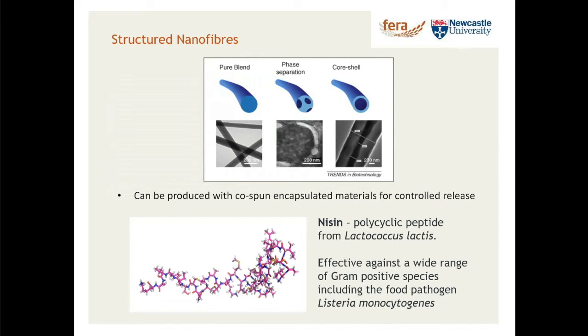So other things we can do with this process, we can spin fibers, but we can also start to spin fibers which contain various other materials as well, and these can be randomly distributed or in a more controlled fashion. And that's kind of interesting because then we now enter into the realms of creating materials which are perhaps biopolymer based, which contain other materials which could also be biological and also released from the fibers. And a piece of work that's being done, and a few people have done this now, is to encapsulate food-grade antimicrobials such as Nisin, and this material is then released out of the fibers, so you get a dual effect. You have the antimicrobial activity of the fiber itself, you have a controlled release of another material which might be antimicrobial or antioxidant, again, this opens up various other possibilities.